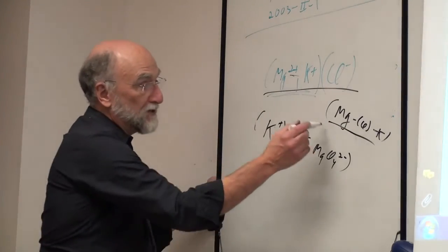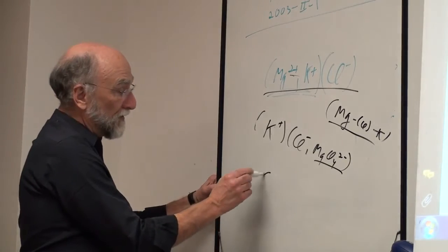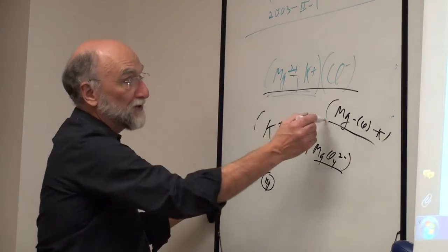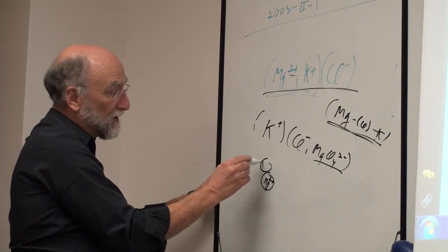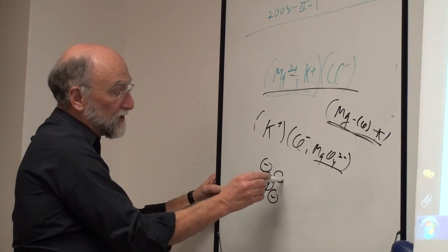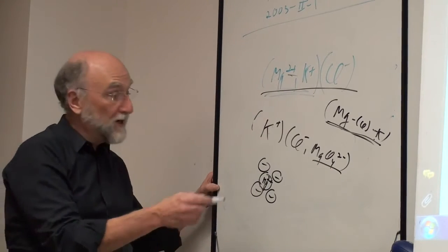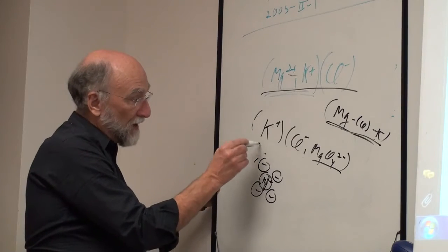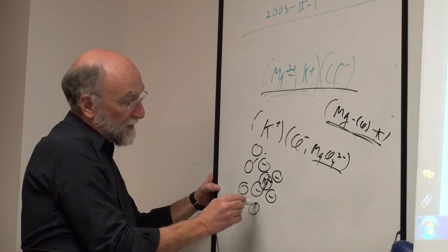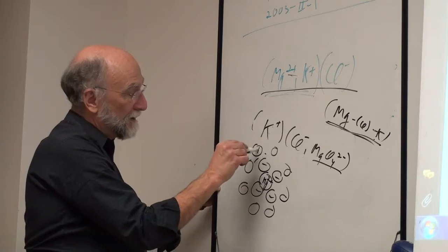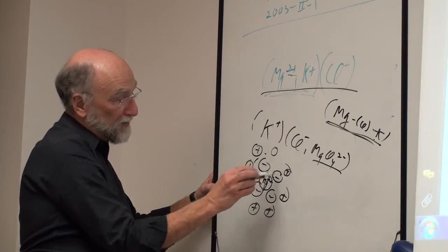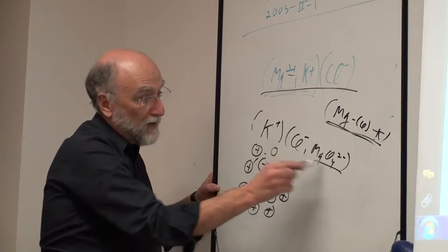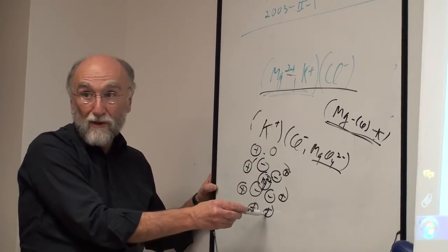So what does MgCl4 mean? What does the short-range ordering model mean? You've got a magnesium here, in your first coordination shell you've got chlorines, and then in the next shell around that, you've got a bunch of potassium ions. So your second nearest neighbors are magnesium-potassium, and they're favored, otherwise you could have magnesiums around it.